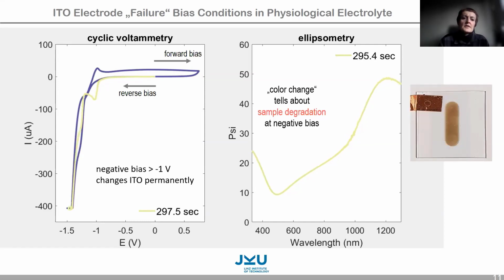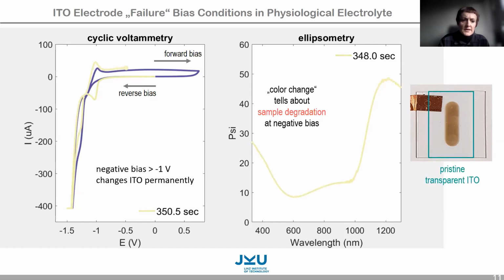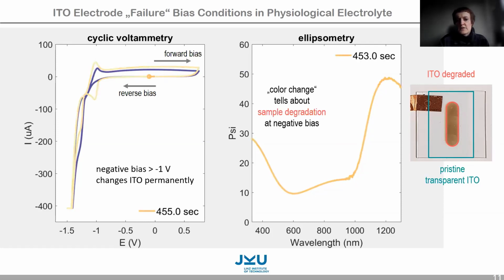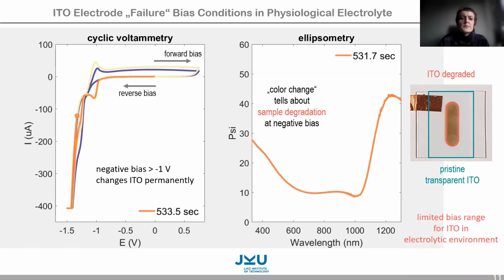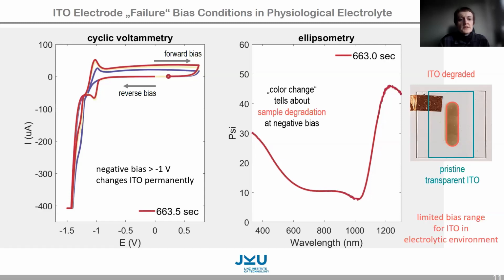This is a picture of the ITO electrode sample for this experiment. The faintly colored area is the pristine, unreacted, and transparent ITO. The brownish colored area is the part of the sample that has been degraded under the electrochemical bias. And clearly you can see the material has lost its transparency. From this experiment, we can learn that there's only a limited voltage bias range which an ITO electrode can tolerate in an electrolytic environment. And this brings me already to my summary.